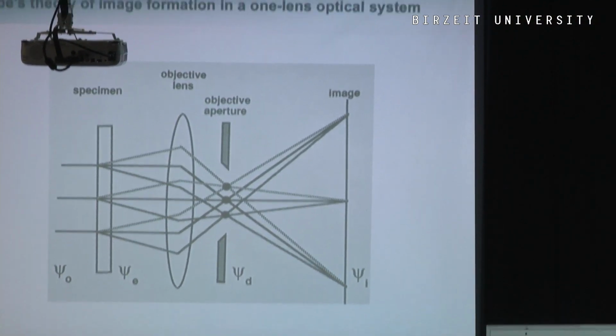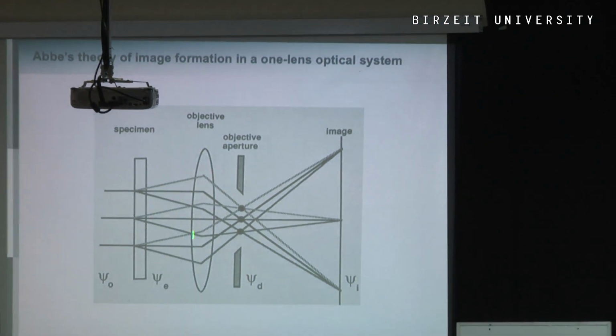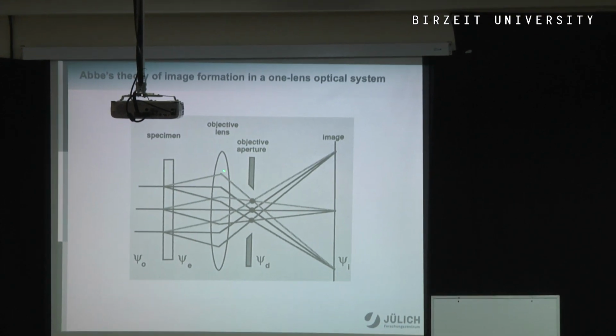And according to this approximation, if we have a plane electron wave passing through a thin specimen, and we have one imaging lens which focuses an image of the sample onto a detector, then in between the lens and the detector we have what's termed a backfocal plane, and in the backfocal plane you focus a diffraction pattern, the diffraction pattern that would normally be formed at infinity.